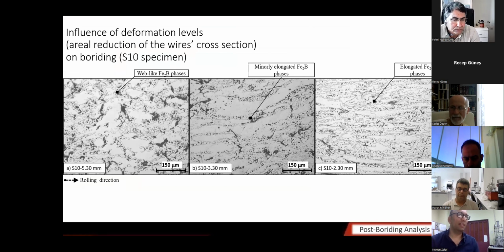Now, the next step is to understand the influence of deformation on the iron boride phases. On the left side is a wire of 5.3 millimeter, and on the right side, there is a wire of 2.3 millimeter. They all belong to S10, the material which was reinforced by 10 volume % reinforcement ratio. You can see clearly that the iron boride phases tend to elongate in the direction parallel to the cold rolling. So actually what we have done is that we have been able to control the morphology, and we have given the iron boride phases an opportunity to change their direction by using cold rolling in the pre-sinter state, and after the boriding, they are elongated in the direction of cold rolling.